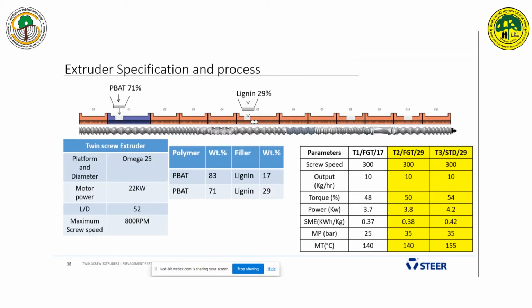We added PBAT from the intake and melted it completely, then added lignin from the second side feeder. This was the fractional geometry technology we utilized, and we used the same process with the standard technology. I have given the example only for fractional geometry technology. We used a smaller 25 millimeter extruder in the lab, adding lignin at 17% and 29%. But in the next slides I'm talking only about the mechanical properties at 29%. These two combinations we have utilized,